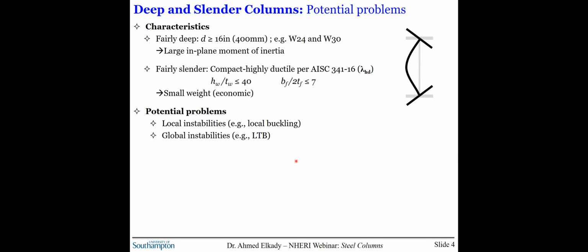Now, these column cross sections typically have depth larger than 16 inches. So we typically see W24s and W30s. And these all have large in-plane moment of inertia, as we want. At the same time, to economize on the steel weight, we select cross sections with local slenderness close to the compactness limit for highly ductile members, as per the seismic provisions. And to give you an estimate, roughly the web slenderness would be 40, and the flange slenderness would be close to 7.